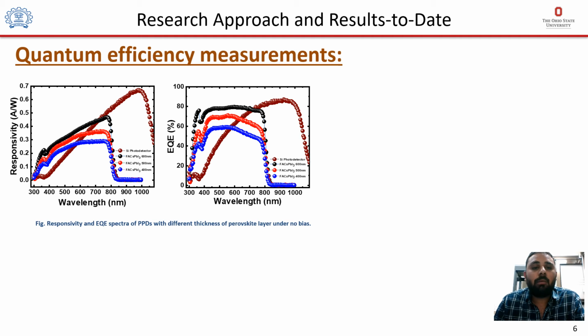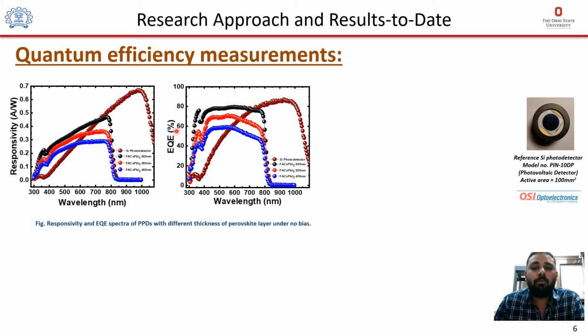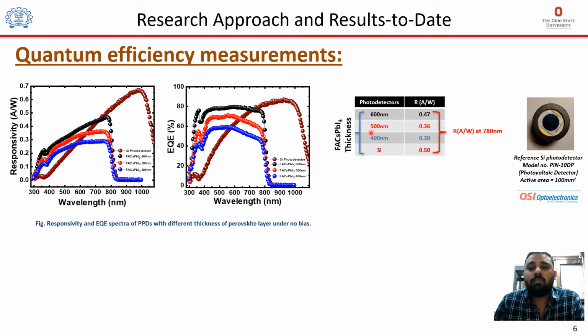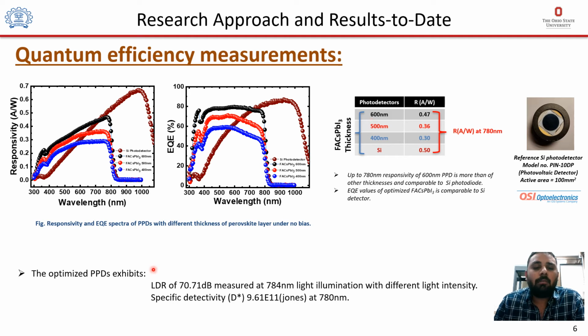Then we have measured the quantum efficiency, which is the responsivity and the EQE, of the devices of three different thicknesses along with our reference silicon photodetector. For our optimized device of 600 nanometer, we got a responsivity of 0.47 amperes per watt at 780 nanometer, while that of the commercial silicon is 0.5, which is comparable to our optimized device. We have also measured the linear dynamic range using a 784 nanometer light, and the LDR value is 70.71 dB. And then we have measured the specific detectivity, which is 9.61 times 10 to the power 11 Jones at 780 nanometer.